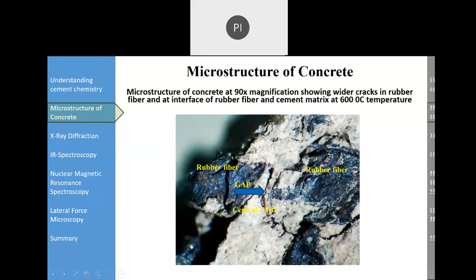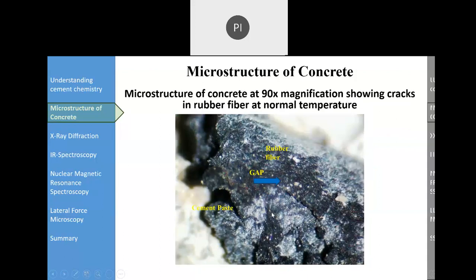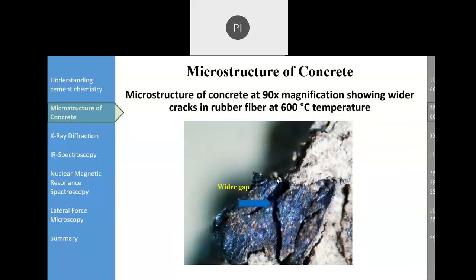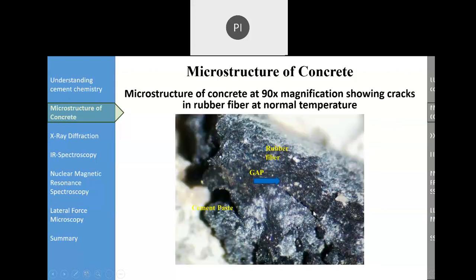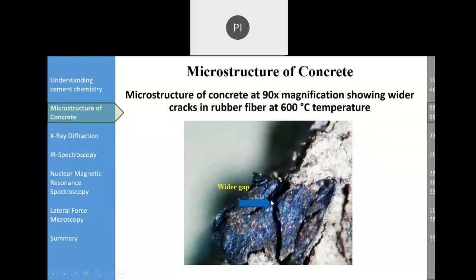Further increase the temperature to 600 degrees centigrade, the gap is increasing further. What is important is that there were cracks in the rubber fiber at normal temperature also. That means during the cracking, at higher temperatures, this crack will also play a certain role. At 600 degrees centigrade, this crack, which was initially of this size, has become larger. So the crack which was there within the rubber fiber has also opened up at higher temperatures.